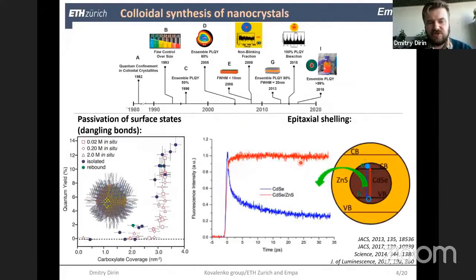And here I would like to switch for a short time to the history of colloidal quantum dots, colloidal semiconductor nanoparticles. For conventional semiconductors like cadmium selenide, it took about 40 years to develop a reliable colloidal synthesis of those nanomaterials, which would allow us to obtain very bright particles with near unity photoluminescence quantum yield, with good control over the PL peak position, so maybe color, and the full width at half maximum of this emission, which is important for color purity.